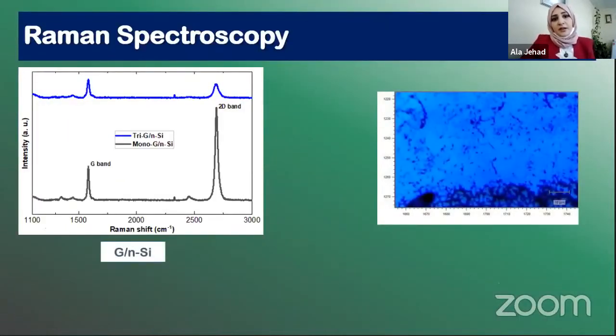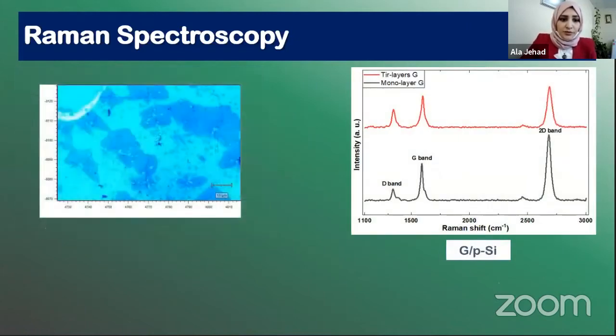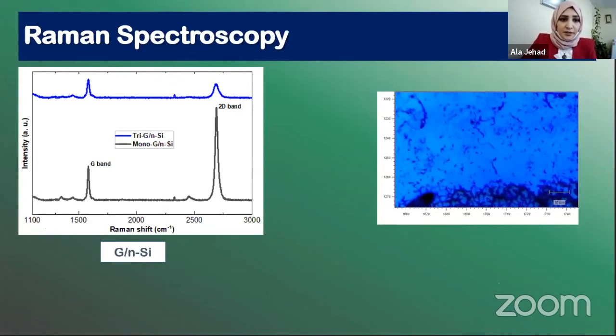First result I have is Raman spectroscopy. As you can see in the first, we have two plots. The black plot is indicating the producing of monolayer graphene. Here we use N-type graphene on N-type silicon. And for the second graph, we transfer graphene 3 times. So as you can see, the 2D band intensity is reduced and became wider.